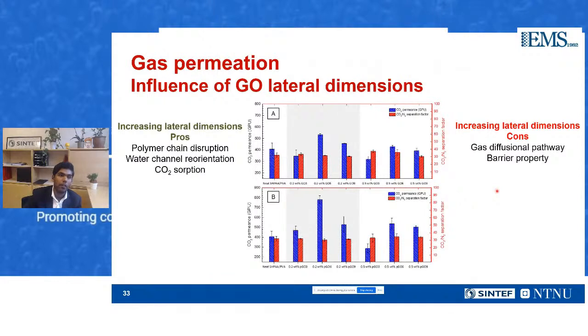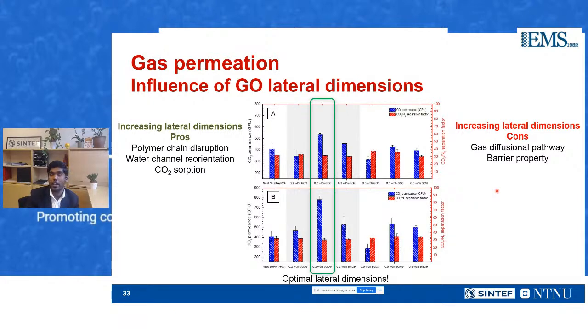So what happens when you have graphene oxide of different lateral dimensions? Increasing lateral dimensions will disrupt the polymer chains even more. That is good. The water channels are also reoriented. That is also good. But then the gas diffusion reduces, and the barrier properties of the graphene oxide itself are going to have an effect. So that's why there is an optimal lateral dimension, where these pros and cons are balanced. And that was something around what we call PGO6, or the graphene oxide 6.